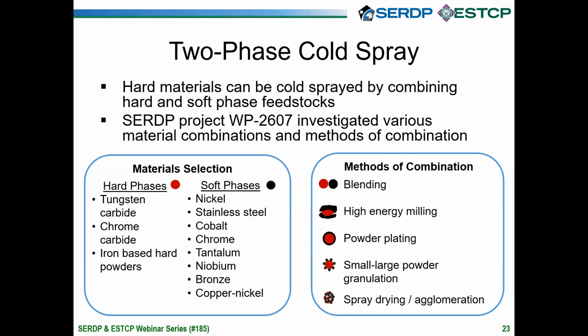So in a prior SERDP project, we evaluated a series of different combinations of hard phase and soft phase materials, as well as different methods of combining hard and soft phase materials. And those methods range from simple blending, in which you just take a hard phase and a soft phase feedstock powder and blend them. So your feedstock has two different types of powder particles. And that ranges all the way to agglomeration, such as through spray drying, where the process yields a single powder particle that contains both hard and soft phases.